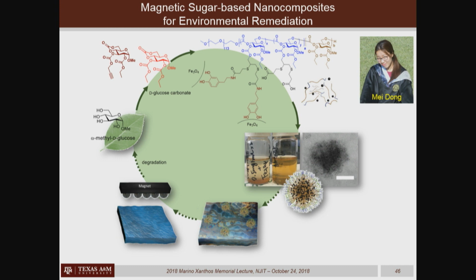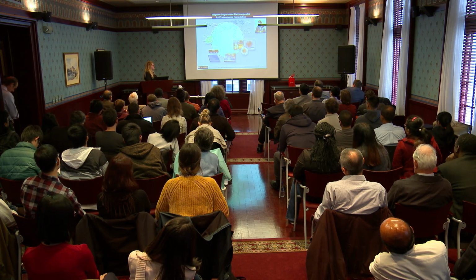Okay, so I'm just going to bring this all back full circle here in this one slide and say that now at this point, Mei is a current PhD student, and she's using the chemistry that Koichiro and Liu had developed and taking these glucose-based monomers, conducting ring-opening polymerizations, and developing polymer materials that can be co-assembled with iron oxide nanoparticles to make these, again, magnetic shell cross-linked nanoparticles, not based on polystyrene and polyacrylic acid, but now based upon hydrolytically degradable glucose-based polycarbonate materials, again, to feed them back into the environment.